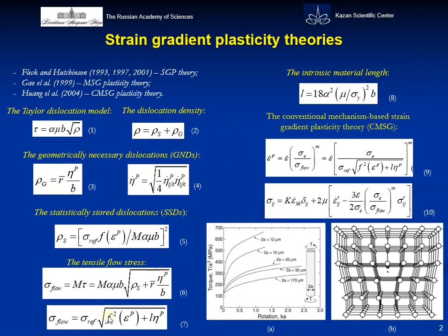The theoretical basis of my work is the gradient theory of plasticity, which was elaborated by Fleck and Hutchinson as strain gradient plasticity, and later modified by Gao as MSG — mechanism-based strain gradient plasticity — and Huang as CMSG — conventional mechanism-based strain gradient plasticity. In our study we used conventional mechanism-based strain gradient plasticity theory, which is based on the Taylor dislocation model accounting for geometrically necessary dislocations and statistically stored dislocations.